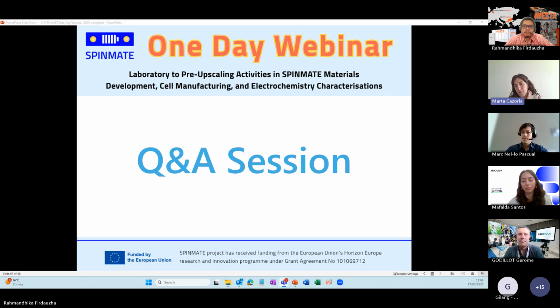So what we do is that we first prepare the catholyte apart, and we leave it time to stabilize, and then we add the active material, to which sometimes we have some reactions, and then the viscosity of our slurry changes, or the texture. You see it when there's a reaction that occurred. In our case, in these materials, at least, we didn't have so much trouble. But I understand what you mean. I think it's the recipe in our case. We had some problems at the beginning, but then it worked well.